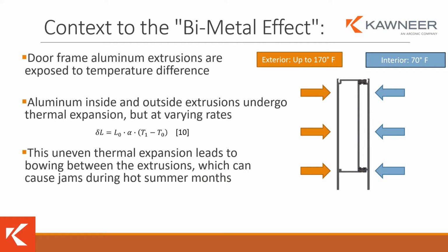The bimetal effect seen in Kawneer's doors mimics the behavior of composite materials when they thermally expand. Composite materials might have two different coefficients of thermal expansion, which will cause one material to expand more than the other, which will lead to bowing. In the context of a door frame, you see a temperature gradient across the outside surface and inside surface. The outside, hotter surface is exposed to thermal radiation and will therefore expand more than the inside surface, which is exposed to forced cooling.